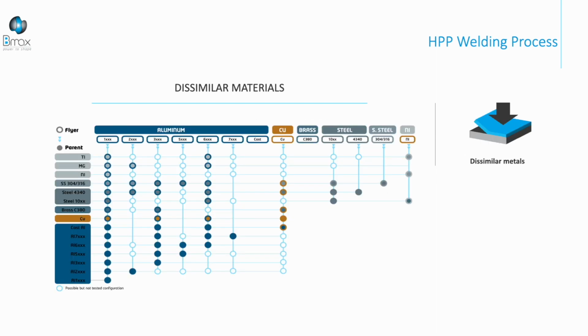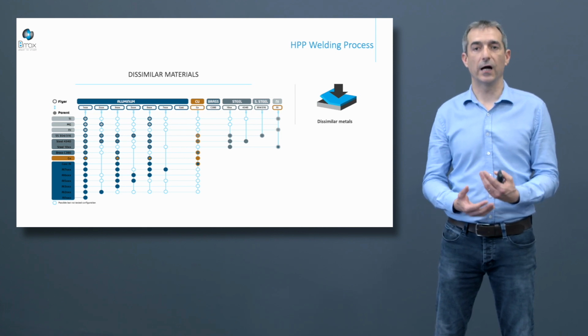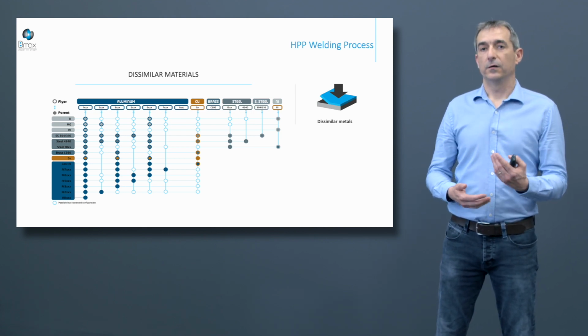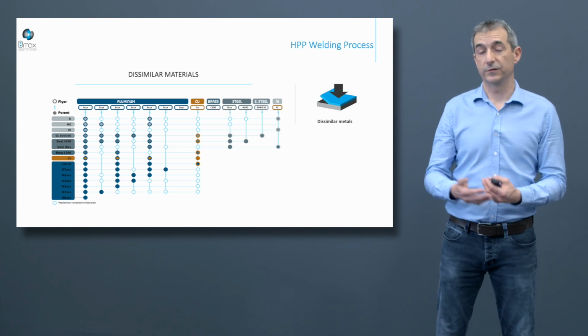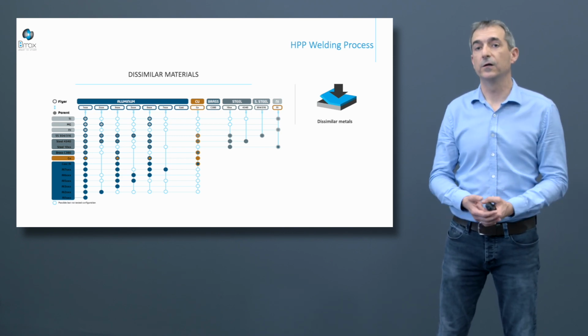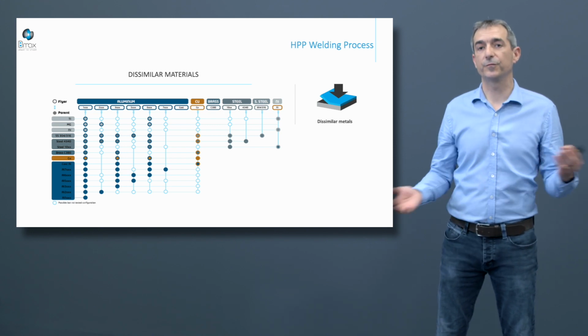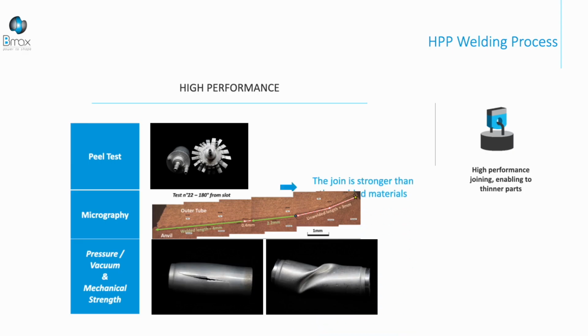After, we are able to form dissimilar materials. This matrix is a simple summary of the combinations of metals we are able to weld or not. Basically, the flyer has to be a good electrical conductor to maximize the efficiency of the system. So that's why usually we use aluminum or copper. In terms of the parent part, the anvil, the target if you want, we can use steel, copper, aluminum. The range of materials is larger. High performance. We can plan any test to evaluate the performance of the joint.